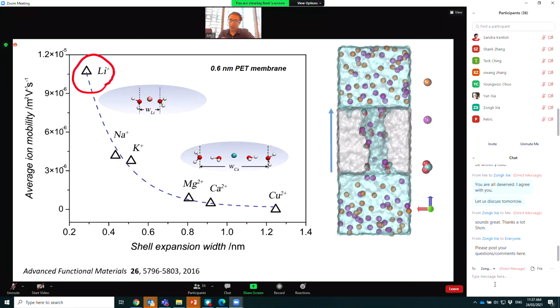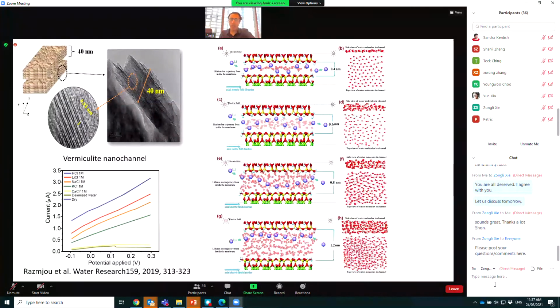The other thing, so having that one, we try to make the nanochannels based on nano-clay vermiculite. We exploited the clay material because we started this project in 2017, and the idea behind using nano-clay was because it's a cheap material, it's very cheap. We just took the crystals, we exfoliated them, and then we reassembled the flakes in a membrane-like morphology. We managed to reduce the nanochannel size, for example, to below 1 nanometer, somewhere around 0.83 nanometer.